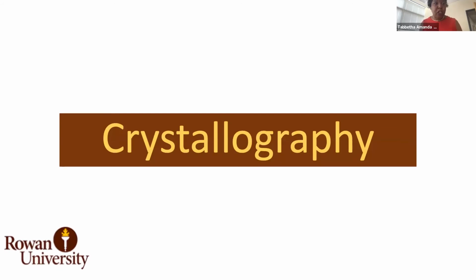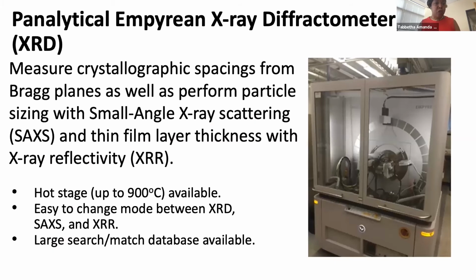So moving into crystallography, we have 2 diffractometers. The first is the Panalytical Empyrean X-ray diffractometer. This one was installed in around 2012, and it's unique in the sense that it has 2 additional features. In addition to being able to get our crystalline spacing for a powder sample or for a single crystal sample, we're also able to configure the instrument to give us X-ray reflectivity, so that if you have multi-layers that are in the nanometer scale, you're able to determine the layer thickness. And then as well, we're able to do small angle X-ray scattering with a different reconfiguration of this instrument.